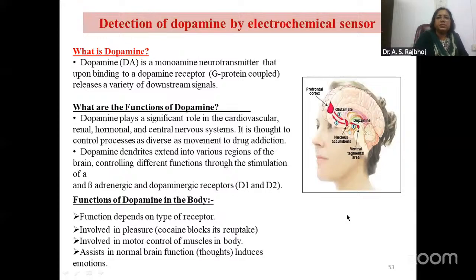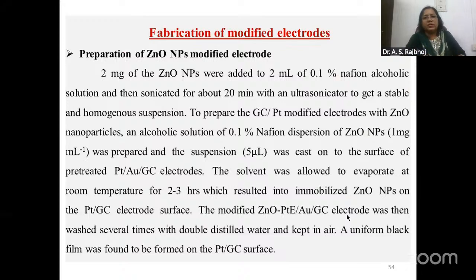and it assists normal brain functions and induces emotions. So first of all, we have prepared the zinc oxide nanomaterial modified electrode. This electrode was prepared by adding zinc oxide nanomaterials to 2 ml of 0.1% Nafion solution and sonicating for about 20 minutes with an ultrasonicator to get a homogenized suspension. Then, to prepare the modified glassy carbon electrode, an alcoholic solution of 0.1% Nafion with a dispersion of zinc oxide nanoparticles was prepared, and the suspension was cast on the surface of a pre-treated glassy carbon electrode. This solution was allowed to evaporate at room temperature for 2 to 3 hours, and then the zinc oxide nanomaterials were immobilized on the glassy carbon electrode. So this has been used for the study.